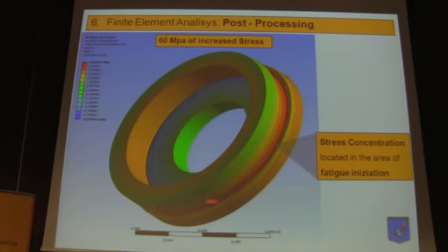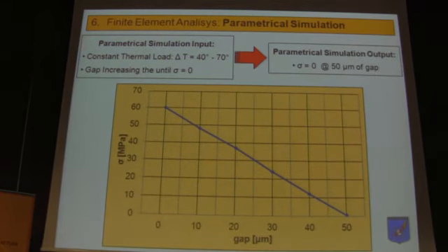And after that, we perform a parametrical simulation, increasing the gap between the cap and the actuator case in order to reach the normal stress condition, so sigma 0. And we find that for 50 microns we have the perfect condition, so this is coherent with the drawing requirements.